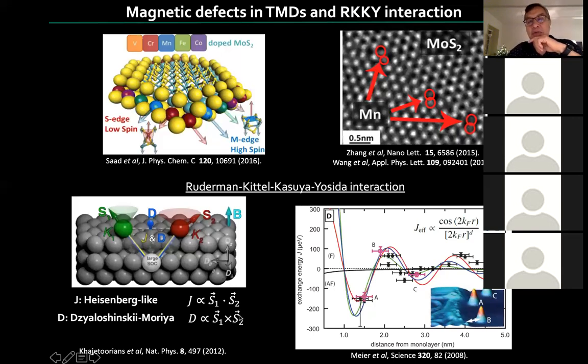But in the Dzyaloshinskii-Moriya, you break that symmetry, because now what you're trying to maximize, again depending on the sign of D, is something that is across from each other. So they're not parallel or anti-parallel, but in fact at 90 degrees from each other, which will be preferred if D is maximum. So there's a competition between the two interactions, which is of interest in magnetic systems.